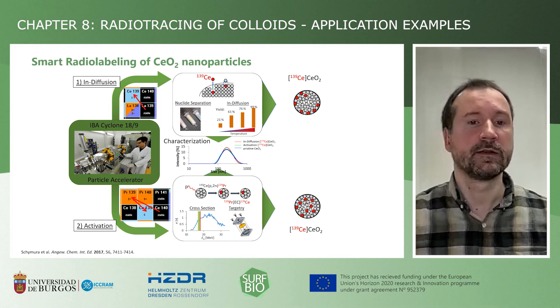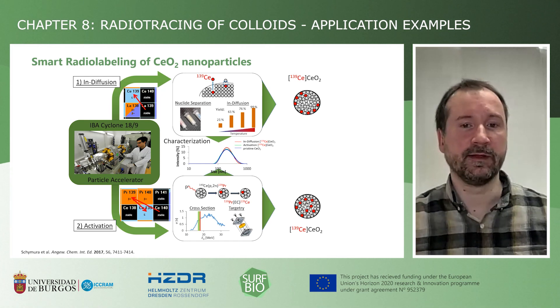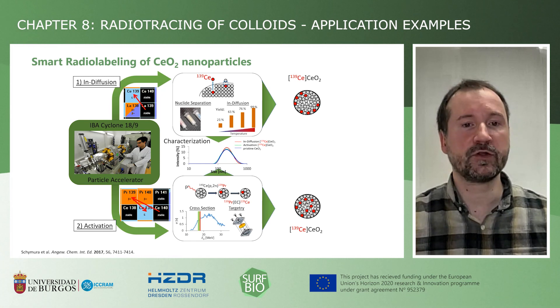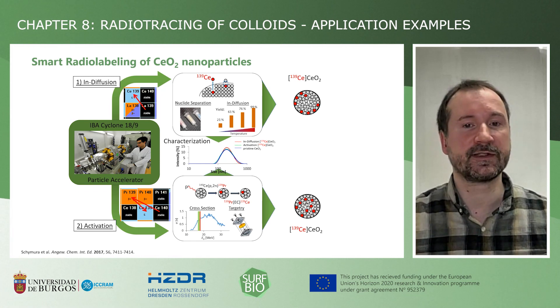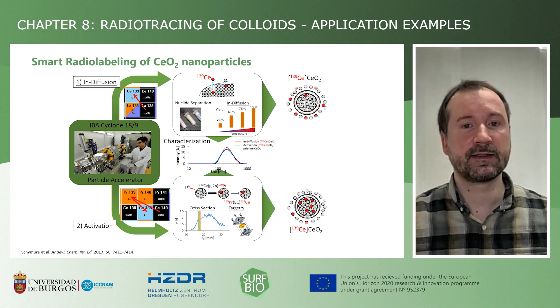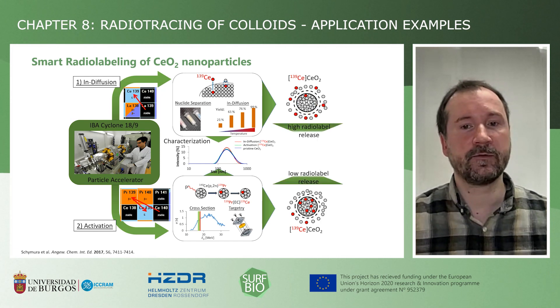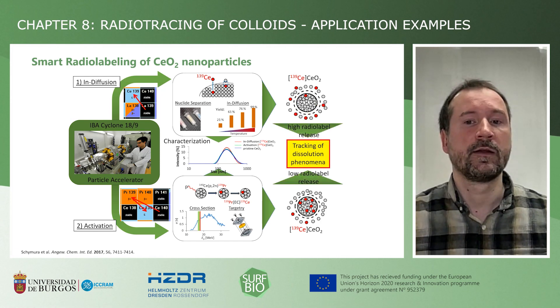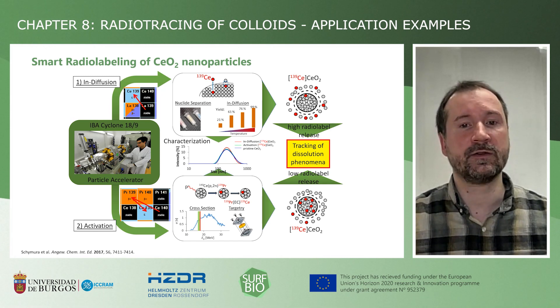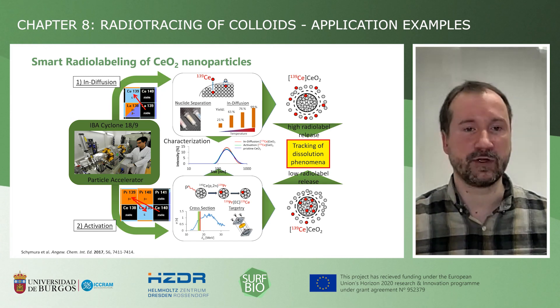However, the radiolabel is distributed differently in the two methods. For the indiffusion method, the radiolabel will sit more closely to the surface of the nanoparticles, while the activation will produce an equally distributed radiolabel. This leads to a different radiolabel release upon dissolution of the particles and enables us to track dissolution phenomena.